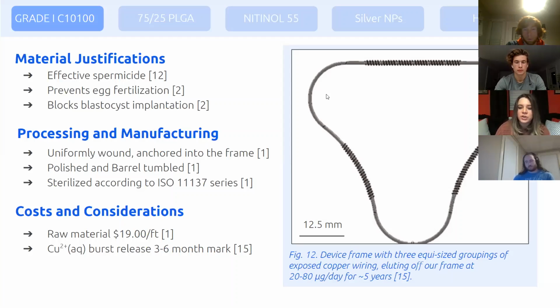The wire has a uniform diameter of 0.255 millimeters. The proximal end of the wire will be anchored into the frame and uniformly wound. The distal end will be tucked into the frame, and the entire frame and the copper will be polished and barrel tumbled to prevent sharp edges in utero. The copper will be sterilized at 40 kiloGray of gamma radiation, and the wiring itself is relatively inexpensive, but the toll it takes in utero is not insignificant.